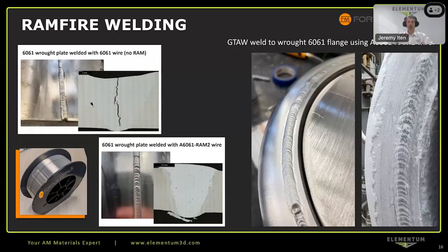Here's some more on the RAMFIRE welding that was performed. And so on the left there, you can see this was a 6061 wrought plate, traditionally produced plate, that was welded with 6061 wire without any RAM in it. And you can see that there's a big crack along that weld bead, and in the cross section there, you can see the cracking that took place. So this is the problem that we're trying to overcome for the welding side, and printing has similar challenges.